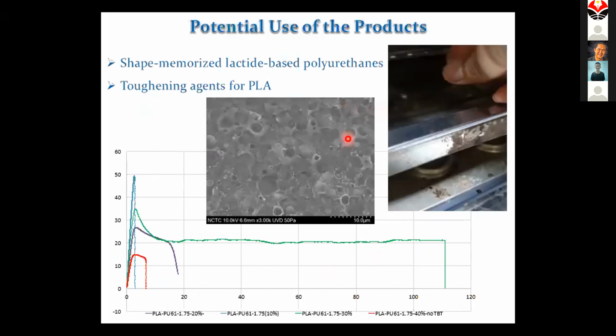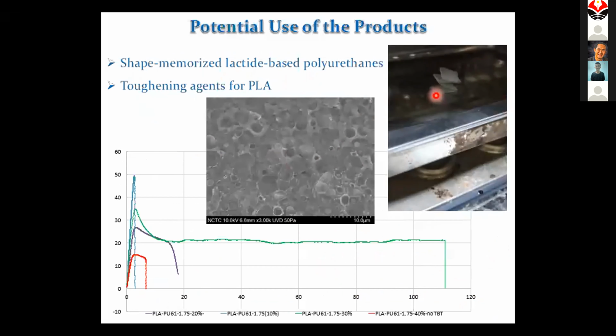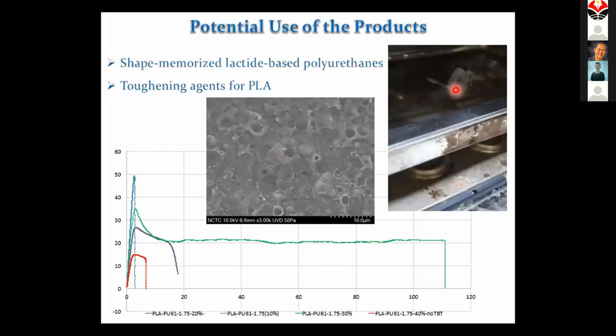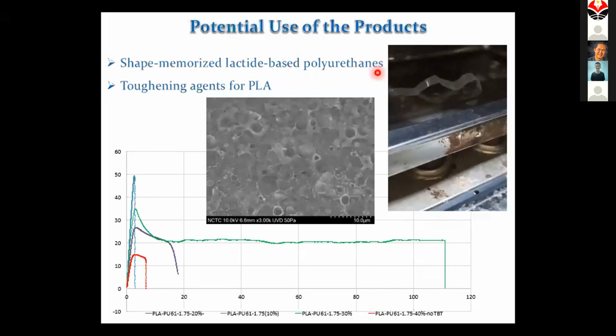These are examples of potential applications of this polyurethane that we get from PLA. The first one is called shape memorized polyurethane. When we make this polyurethane, we can return them to their original shape by heating them at a temperature higher than the TG. For example, when we put this back into an oven at around 60 degrees Celsius, they turn back to a linear structure. This is called shape memorized polyurethane.